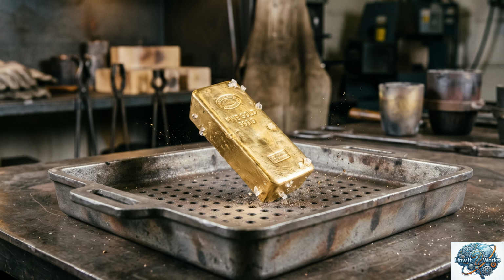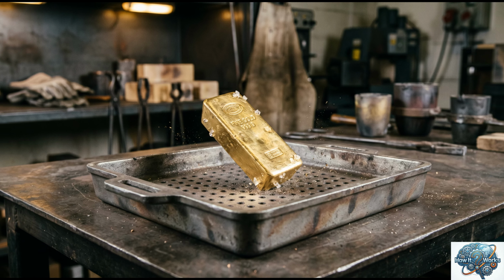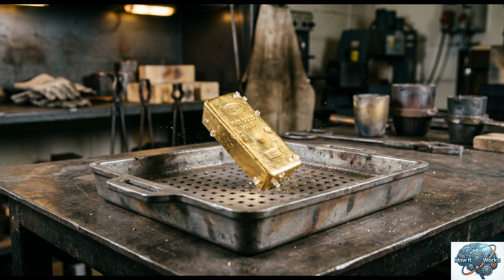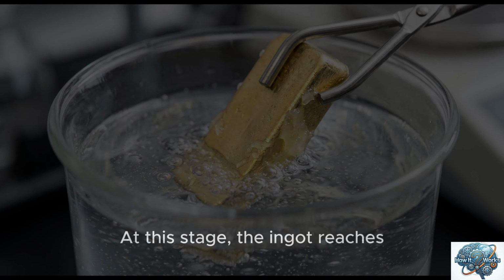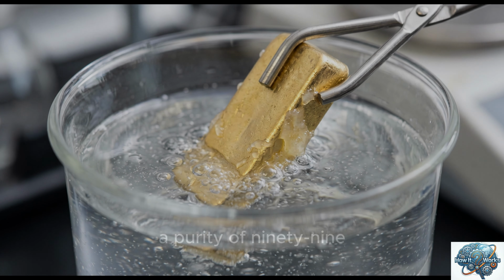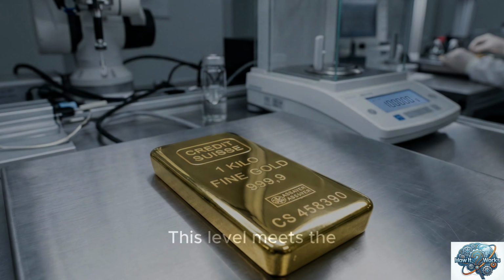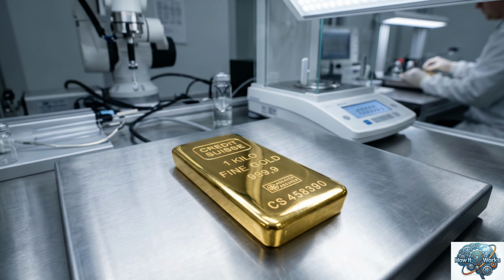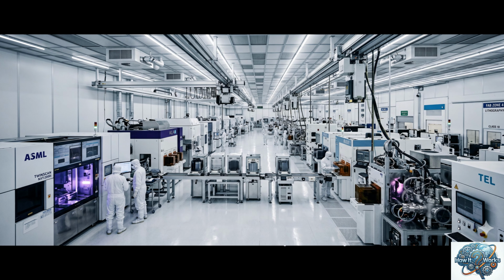Residual borax remaining on the surface after casting is removed in a mild acid bath. At this stage, the ingot reaches a purity of 99.9%. This level meets the standard of 24-karat gold. However, for aerospace, space, and semiconductor industries, this level of purity is not sufficient.